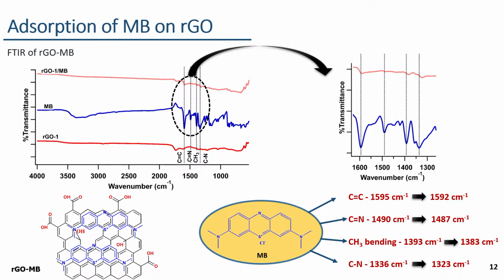Here these red shifts are possible due to the interaction of these methylene blue molecules with the remaining hydroxyl groups at the edges of the basal plane and the defects. So, because of these interactions, the adsorption of methylene blue in parallel orientation to this reduced graphene oxide through the pi-bond interactions is possible. Therefore, these FTIR results reveal that methylene blue is adsorbed onto GO and RGO in 2 different orientations. Methylene blue is adsorbed onto the graphene oxide in vertical orientation through electrostatic interactions, while it is adsorbed in parallel onto the reduced graphene oxide through the pi-bond interactions.